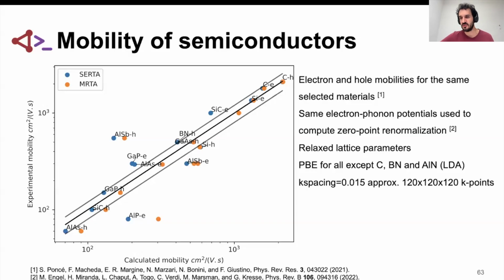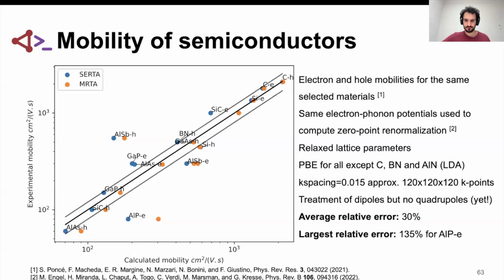Roughly 120 by 120 by 120 k-point sampling, and we have the treatment of the long range part, but no quadrupoles. So the average error is about 30%, so we do get close to experimental values. Of course, the experiments themselves also have some variability, and the largest relative error is for aluminum phosphide, the electron mobility.